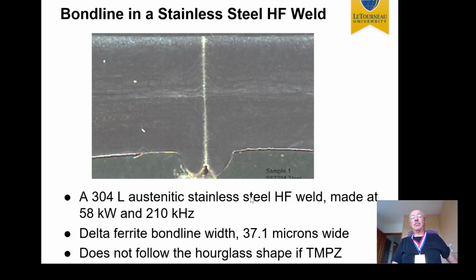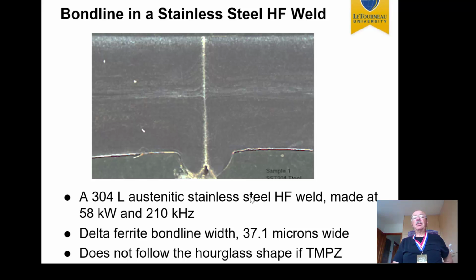The bond line is only 37.1 microns wide, and I will be talking about the width of this bond line several times, but they never really exceed 60, 80 microns. Only in abnormal cases it's wider than that. Yet it will always remain parallel edges, and it will always be in the middle. So please take note of that.